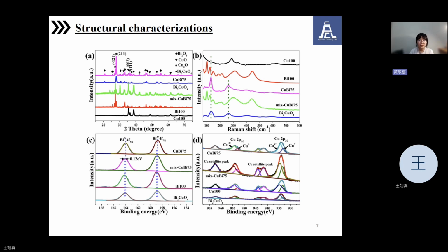The CuBi75 shows a slight positive shift in the Bi ions' binding energy compared to mixed CuBi75, suggesting a stronger interaction between Bi and Cu in the alloy structure. Picture D is the XPS spectra of Cu. The CuBi75 contains both cuprous and cupric ion states. The satellite peaks and relative intensity differences reflect the electronic interaction between Bi and Cu, which can influence the catalytic performance.